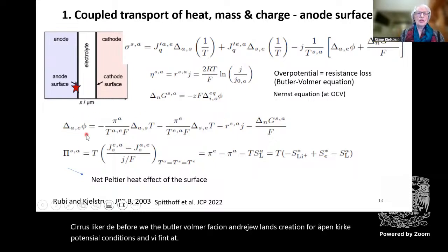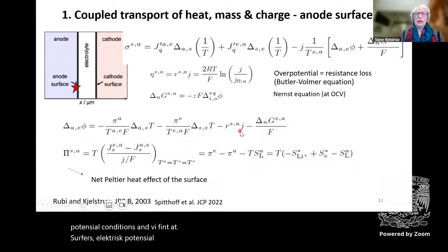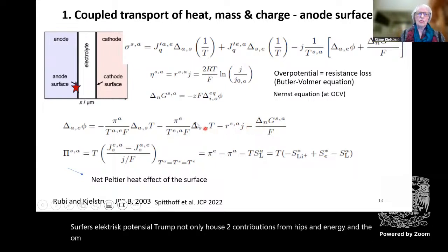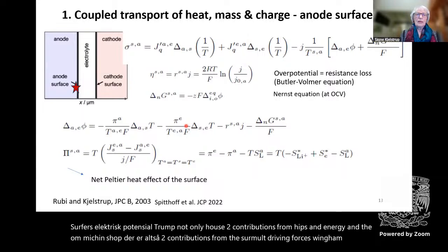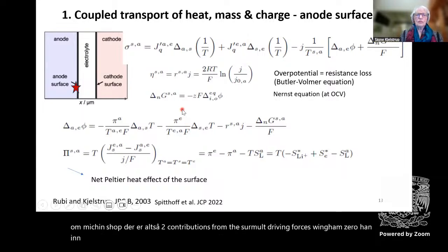And we find that the surface electric potential jump not only has the 2 contributions from Gibbs energy and the ohmic potential drop, there are also two contributions from the thermal driving forces being non-zero. And in addition, I can use the flux equation. This is not shown, but I can find the net Peltier heat effect of the surface.